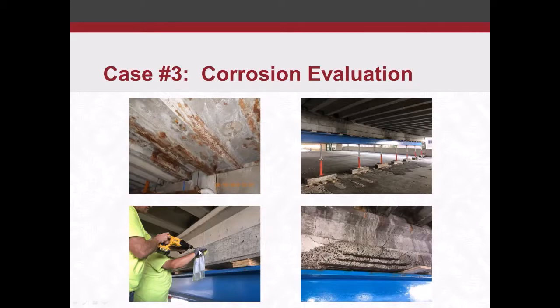We took some chloride samples from the beam at various steps, from 0 to 1 inch. So we just take a hammer drill and basically we're pulverizing the concrete from 0 to 1 inch, and then we analyze it. And we were getting chloride results of about 1% by mass of concrete, which is a lot, considering the limits are usually like 0.06 or 0.1 or something like that.